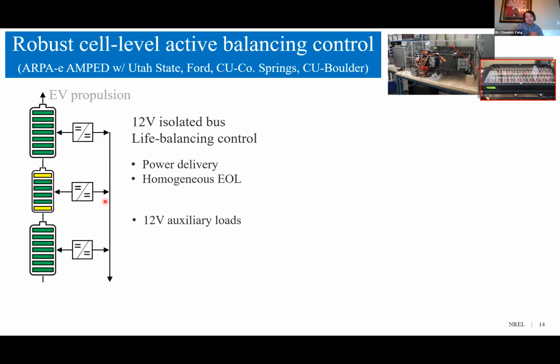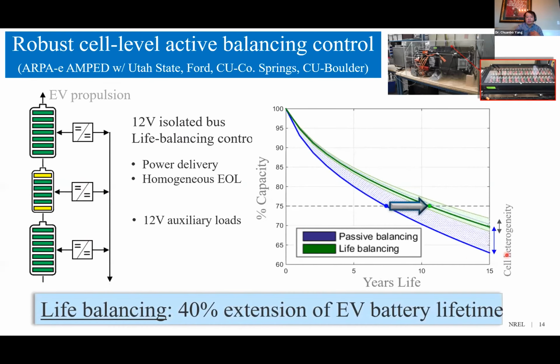Existing DC-DC and battery thermal management is replaced with an integrated modular BMS DC-DC. Life balancing leads to reduced capacity imbalance that can be caused by factors such as pack temperature gradient and slight manufacturing variance among cells, increasing lifetime and relaxing the thermal management system. Range is no longer limited by the weakest cell in the pack.